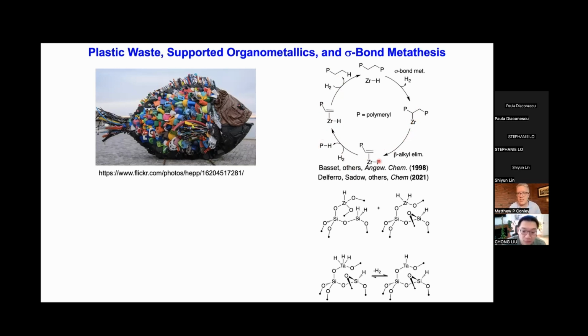And these are purely statistical in nature because you're driven by this beta alkyl elimination event that happens statistically dependent on the metal itself. The tantalum sites down here also engage in this reaction chemistry, but both of these neutral materials, which are excellent in their own right, show very slow reaction rates.